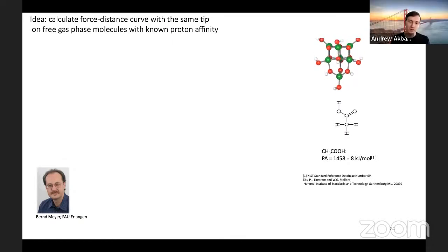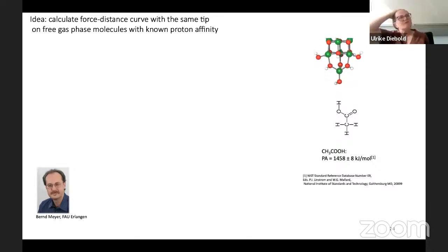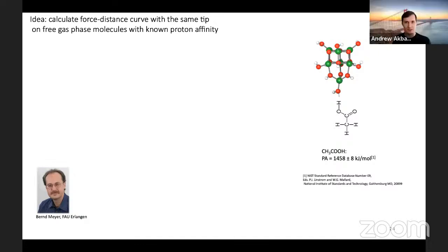Okay, interesting, because there are so many things. I mean, DFT itself is so dependent on the functional and so many other things. Yes, I was just wondering. Well, that's why, for example, for the TiO2 surfaces, we collaborate quite a bit with DFT people, and the question is how localized the electrons are. Our experiments have been helpful to find out what kind of DFT plus U Hubbard U to take to really find the right localization for titanium dioxide to really model things accurately. So sometimes what we do in an experiment is a benchmark for the DFT calculations because we have this nice atomic control. Okay, that's exactly what I was saying. So the two approaches converge.